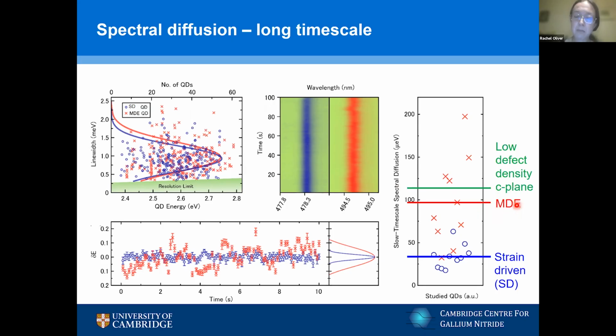The trouble is we're not really making a fair comparison here, because our droplet epitaxy dots, because of the immaturity of the A-plane system, contain a lot more defects than the low defect density C-plane material we commonly worked on when we mostly focused on the C-plane. If I want to look at an equivalent defect density on the C-plane, I actually have to make my graph a bit longer, because my high defect density C-plane material, which has a very similar density of these crystal faults to my A-plane material, has a much, much higher extent of spectral diffusion. So we think we really are achieving improvements by moving to the A-plane in this spectral diffusion issue.